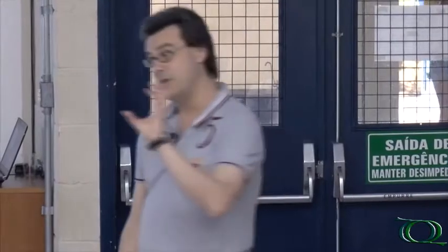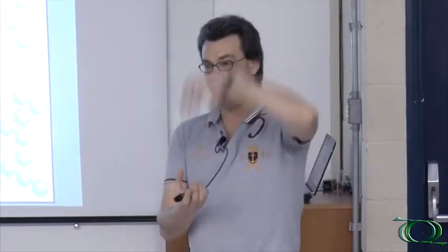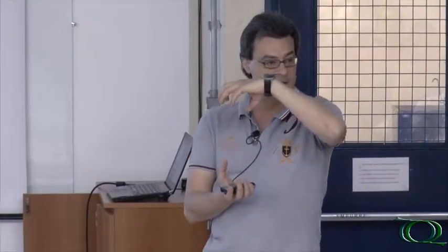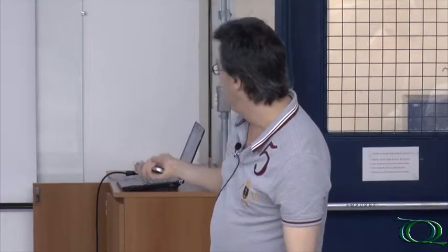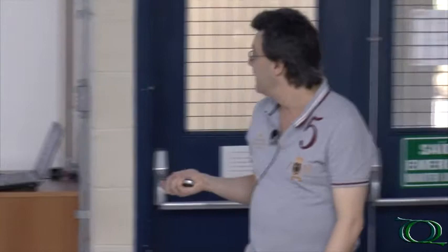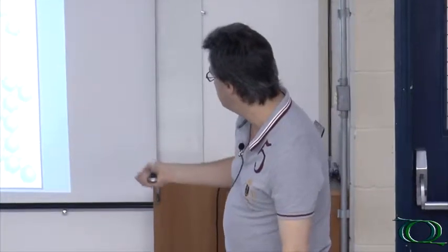So then we realized that we really have not only an effect of the hydration energy, but also a cavity effect. So the place where the cation is going to be attached has a size, and only cations that match very well with the size are going to be strongly retained there. So this is what we expected to see, either this structure or this structure, and then we did some STM, and we indeed could see the cations attached on the surface. What we saw is that this is the way they attach, not this one.